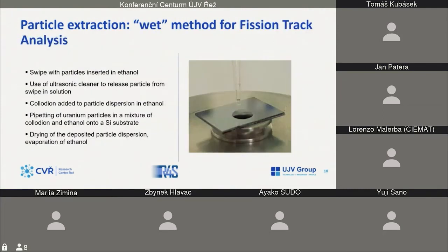And the wet method is based on inserting particles into a solution of ethanol and collodion. The particles on the swipe, or the whole swipe, or part of the swipe, is inserted into ethanol, and we use an ultrasonic cleaner to release particles into the solution.